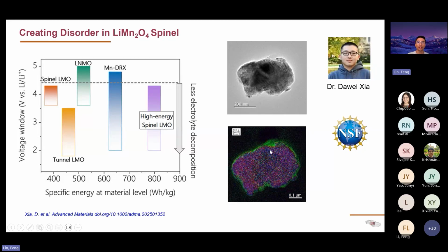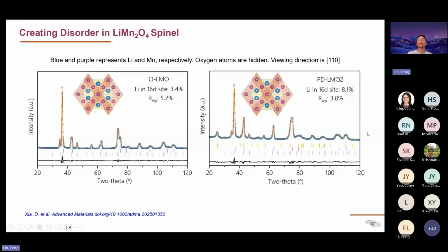The process that he uses is really simple. Just ball mill, mechanically mill, the spinel with graphite materials, creating a carbon coating on the surface. On top of the carbon coating, we actually found that we are creating disordered materials. So spinel is a cubic structure, and after we perform mechanical milling, we get somewhere between disordered spinel and disordered rock salt type of structure locally. This is done through neutron diffraction. We can figure out the structural disorder. So the sample is labeled as partially disordered. It's not totally disordered, it's partially disordered.